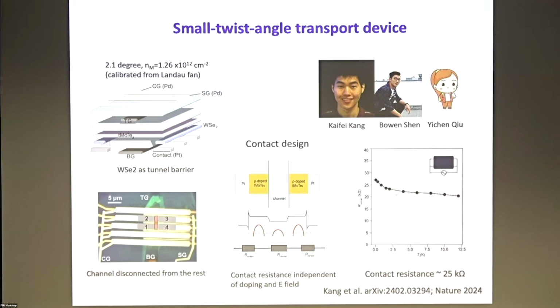Okay. And this is the contact resistance that we measure as a function of the temperature. Even down to millikelvin temperature, we can get a contact resistance about 20 to 30 kilo ohm. This number may not be very impressive for people doing graphene, where you typically get 1 to 2 kilo ohm or 1 kilo ohm or something like that. But it's actually already pretty good. It's, I would say, very good already for the twisted TMD devices.